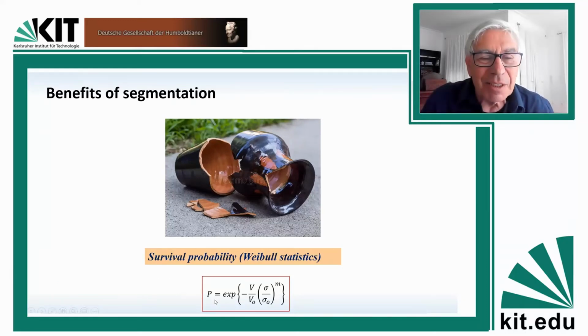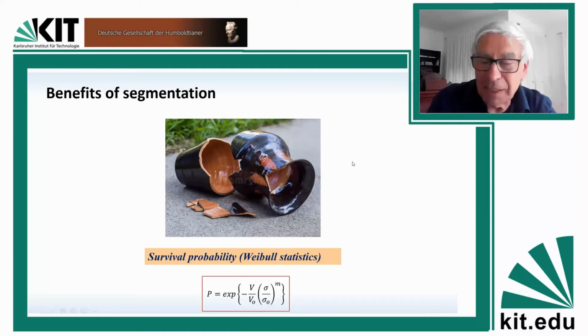Now, this is the single formula I have in this presentation, by the way. It gives you the survival probability of a structure under a stress sigma. Following the so-called Weibull statistics, this survival probability not only depends on the stress, but also on the volume of the part, or structural member we are talking about. And that means that by decreasing the volume, you increase the survival probability.